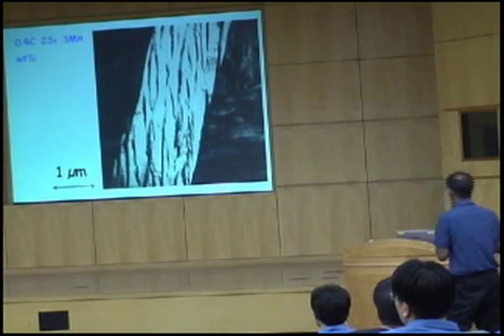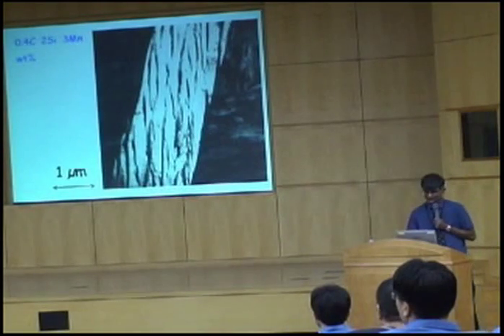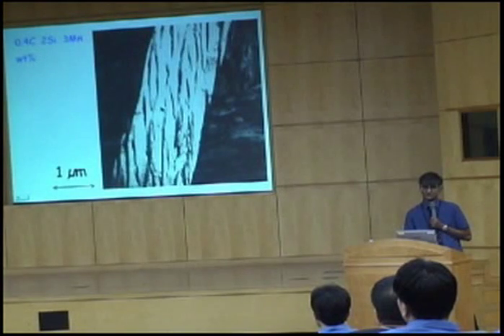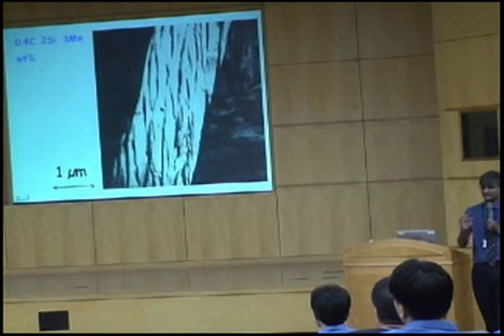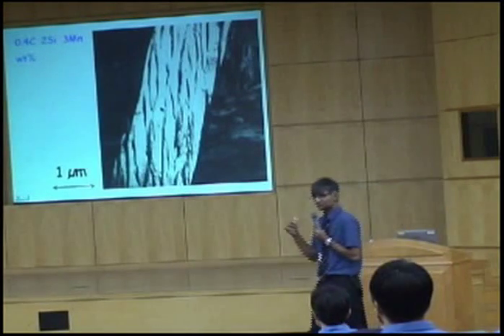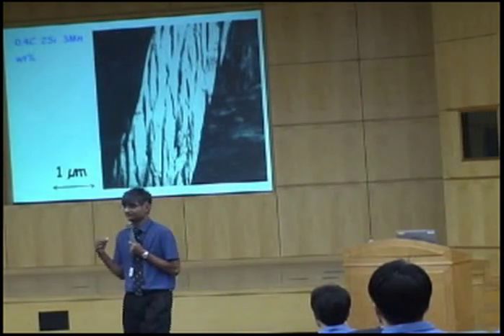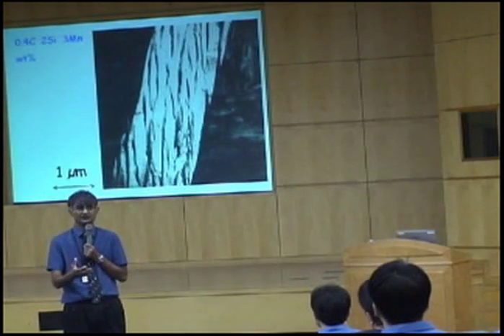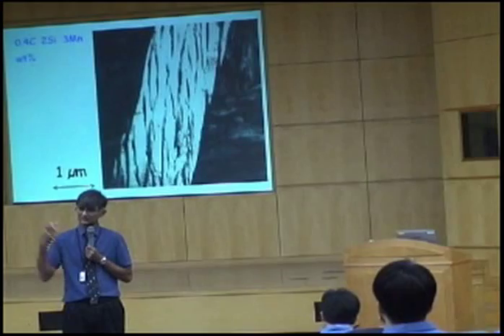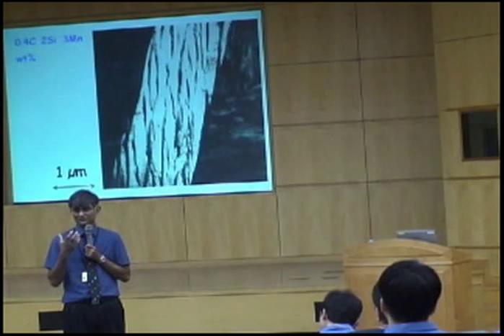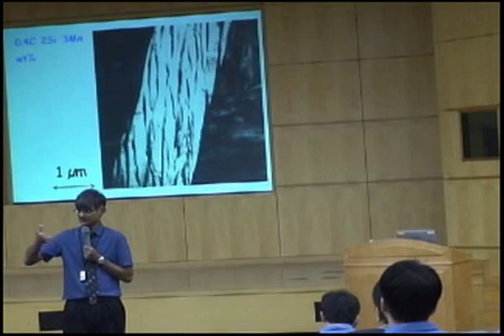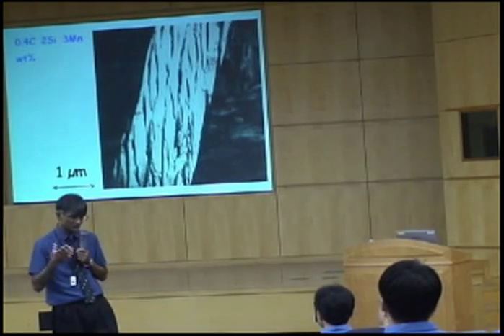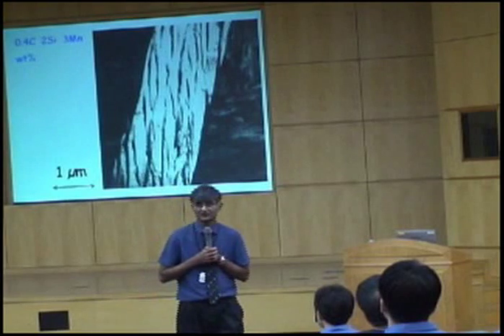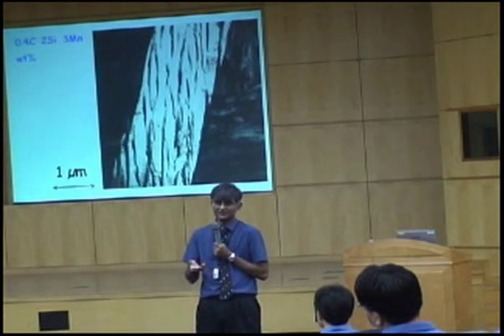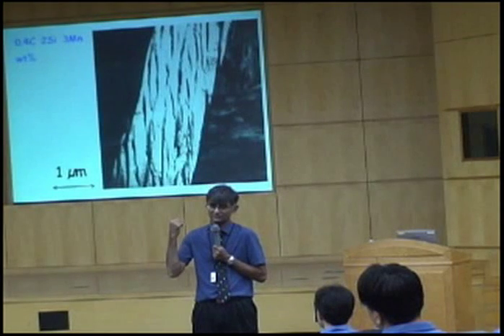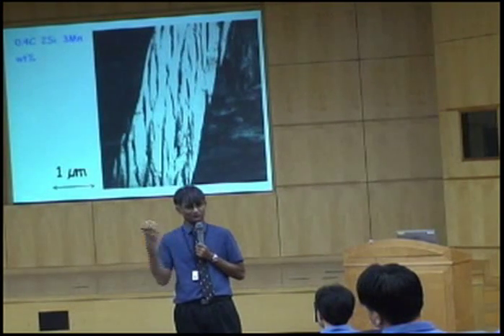Yeah, we not only have those films, but we have a very, very fine grain size. This is of the order of a quarter of a micrometer. And there is no thermomechanical processing which can produce a grain size of a quarter of a micrometer. Okay? Here we produce it naturally by phase transformation. So this looks like it's a wonderful structure where we have very fine grain size. We have a nice austenite dispersed between the plates that should give us a good composite toughness. And we are only using the carbon to stabilize the austenite. There's no expensive alloying element. So let's look at the toughness of this wonderful microstructure.